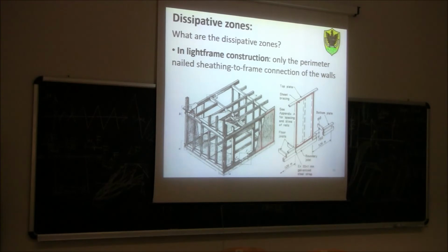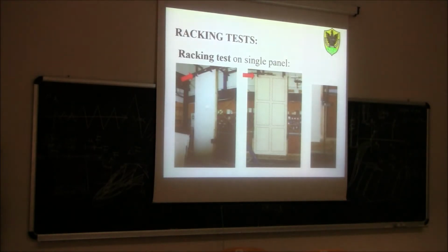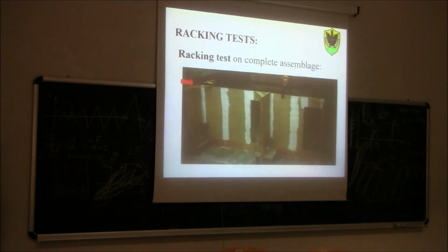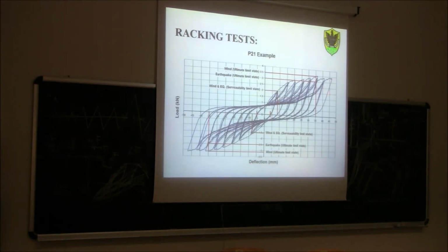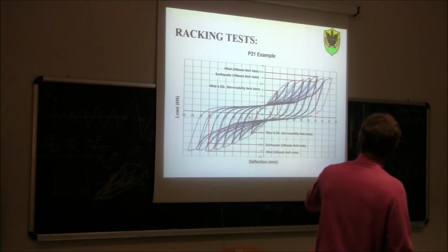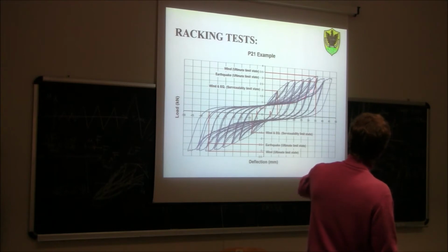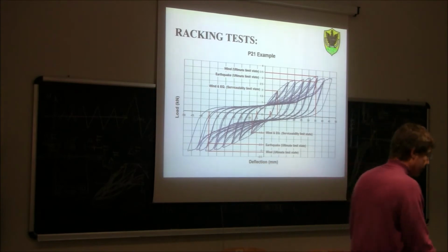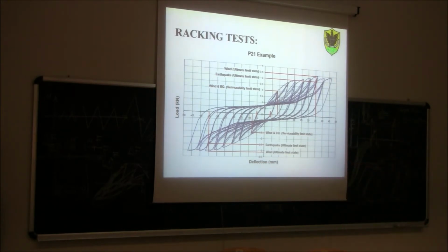Everything else, all the other members, will have to be over-designed with respect to the dissipative zones. Okay? Again, if we do a cyclic test like before on a wall, where we make sure that only the nail connections on the perimeter of the wall dissipate energy, you see, we will find this kind of hysteresis loops. Again, those loops look, as you can see, quite fat, meaning that the structure is able to dissipate energy, and meaning that we can use a significant value of the behavior factor.